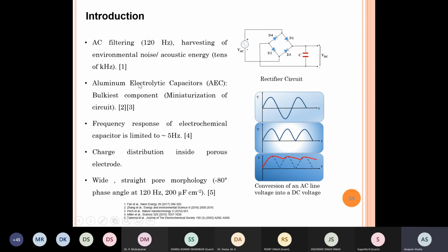Okay, so this is what is done in all filtering circuits, and aluminum electrolytic capacitors are used. Okay, as we were mentioning in the first part of the talk, they remain the bulkiest component simply because the amount of capacitance that they have is about 20 to 40 microfarads per centimeter square. On the other hand, all the electrochemical capacitors that we talked about, carbon electrodes with high capacitance, cannot respond as a capacitor for signals beyond 5 hertz. As soon as you go to 10 hertz, there is no capacitive behavior shown by them. They only show behavior like a resistance, and that has to do with higher ESR.